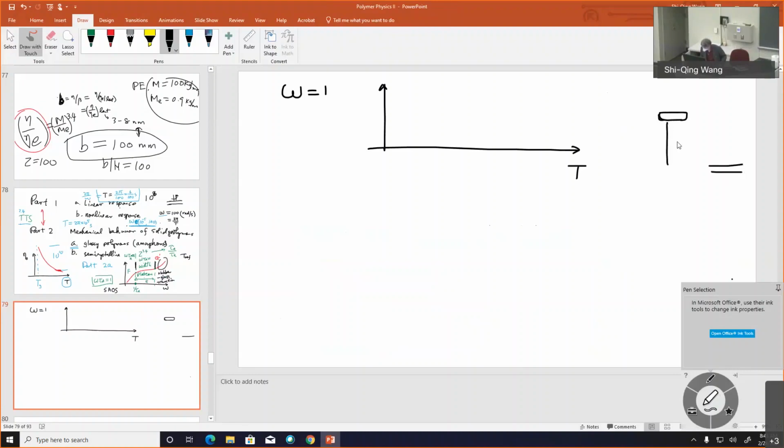When it's in the solid state, you may also have what's called a dynamic mechanical analyzer, DMA, where you do it in a tensile form. So you have it under pre-tension, and then within that pretension, you do a little back and forth. There are two options. This is for the solid state part, and this is more for the liquid state part. You may have both instruments to get this full curve.